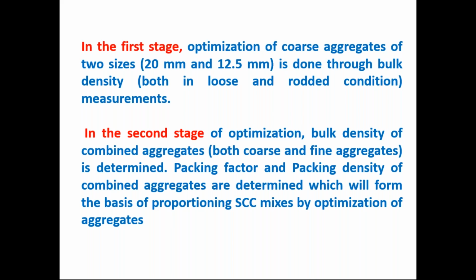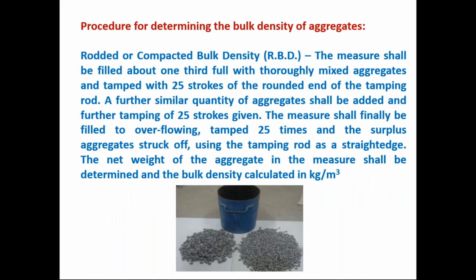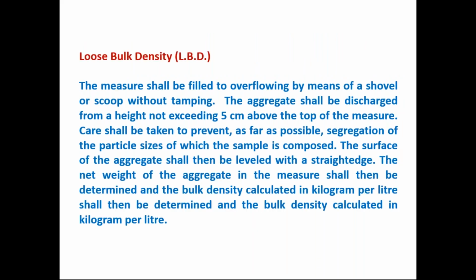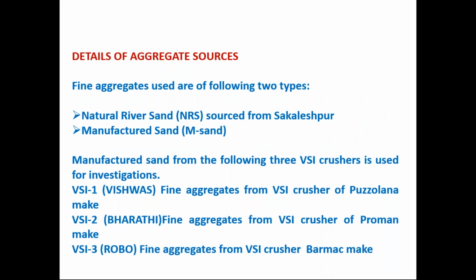In the second stage, whatever you have optimized in the first stage of coarse aggregate, go for the optimization with the fine aggregate also, that is combined aggregate. So there also you will find out loose and rodded bulk densities. We know the procedure very well. Bulk density can be measured with a cylinder having known volume. We give 25 strokes and fill it up in 3 layers, and we will get the required bulk density in rodded condition as well as in loose condition. For loose bulk density, the measure shall be filled simply by putting the material in, and again measuring the weight and the volume. Weight by volume will give the loose density.